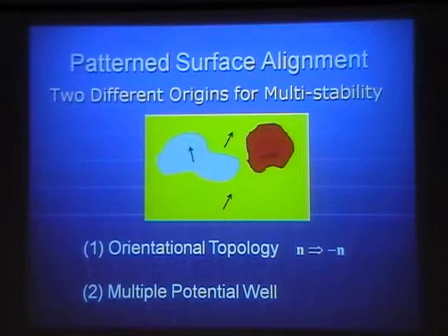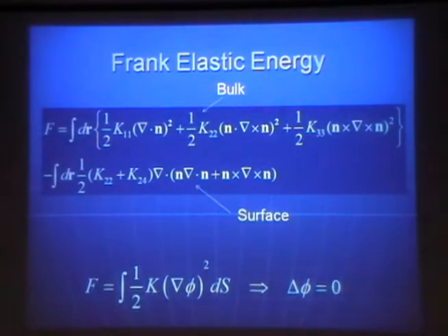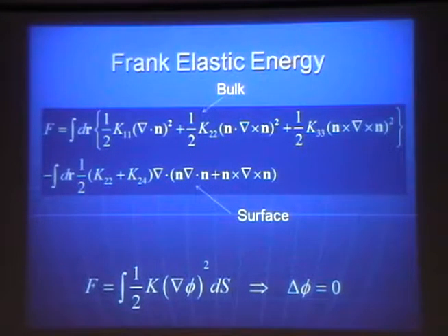And so the liquid crystal director doesn't have any singular direction. Normally it has double-ended arrows, but in order to expose the topological characteristic of the orientation of the surface, I attach only a single head. And so once again, the elastic energy is supplied with surface contribution, saddle-splay.